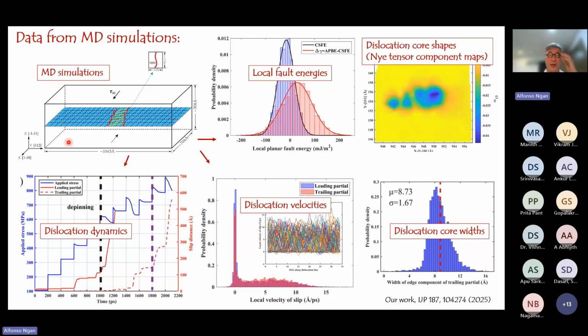So these data could be local fault energies. For a very localized pixel point, for example, you can back out what is the local fault energy, be it the CSFE for the leading partial or the difference between APB and CSF for the trailing partial. So you can look at that distribution, for example, or you can analyze the dislocation core using, for example, the Nye tensor plot, and then you can analyze the width of the partial dislocation. That will be another type of data you can generate from the MD simulation.